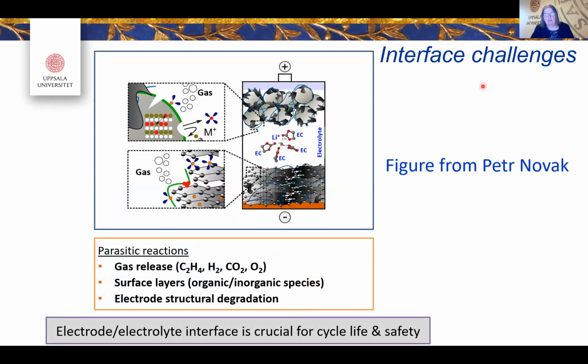I was given this figure from Petr Novak's group at PSI. I think it summarizes really well the difficulty we have on the surface with gas formation, with rearrangement of the electrode structure, which can lead to degradation, and also surface layers, organic and inorganic species that can form but also be destroyed. And we have particle cracking when we are cycling. That also leads to fresh surfaces reacting with the electrolyte.